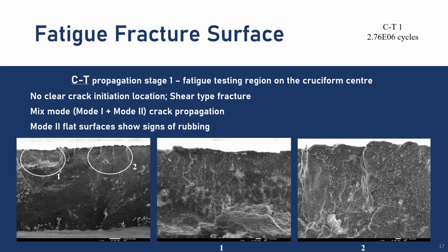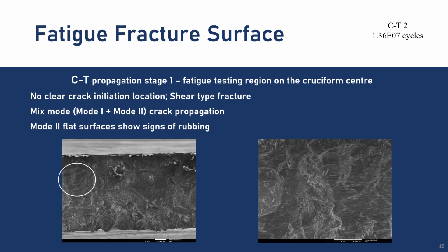Now, observing the CT and comparing it to the TT, we can clearly see there is shear type fracture on the CT specimens. We see especially the mixed mode between mode 2 and mode 1 crack propagation, especially on the surface, where in the interior of the crack we can sometimes see mode 2 flat surfaces showing signs of rubbing.